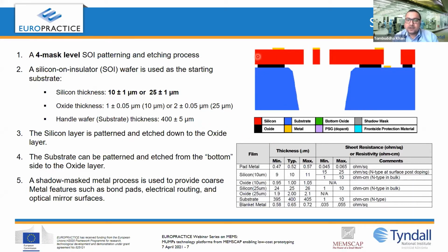The device is actually patterned from the top, and the actual device that you design will be on the silicon layer. The device will be released by backside etching of the substrate, followed by the removal of the oxide, the dry etch of the oxide. And the metal layer, which you use for bond pads, electrical routing or optical mirror surfaces, is done by a shadow mask metal process.